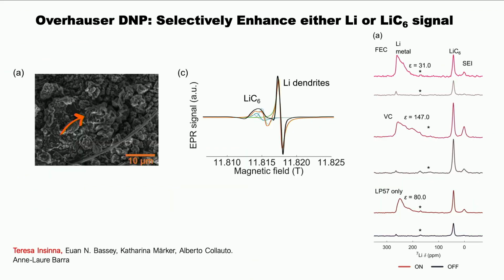my student put in this massive image of this graphite, and this little arrow is meant to show you that there are some dendrites. They're very difficult to see, but you can see them beautifully by the ESR. So here's the signal of the lithium LiC6, and here's the dendrite signal. And what that means is you can irradiate selectively either the LiC6 or the lithium dendrite, and you can enhance this passivating layer on either the carbon or the lithium metal. And so this is an example where we're irradiating the lithium metal. And you're seeing we're getting these massive enhancements of that lithium metal and smaller ones of the lithium carbon itself.